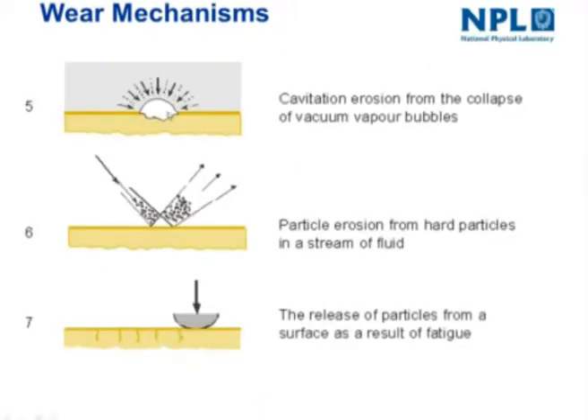Cavitation erosion is when you get collapse of vacuum vapor particles, bubbles in a fluid, and the stress waves that are generated through that cause damage to the materials that lie underneath. It can be quite severe actually. You would think that bubbles don't create much damage, but they can do. And a typical well-known example of this is propeller blades for ships. Particulate erosion is also critical, and this is where you get hard particles in the stream of fluid hitting a surface and causing damage to the surface.